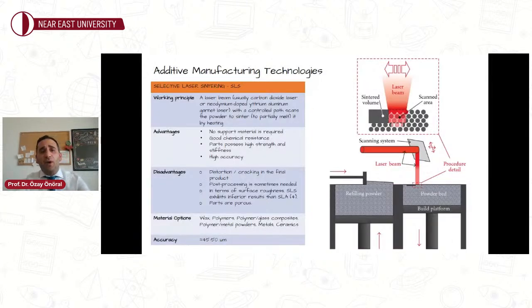SLS technology is another one that is so common in dentistry and allows the creation of 3D models by consolidating consecutive layers of powder, including metallic powders. In this method, a laser beam, commonly a carbon dioxide laser or a neodymium-doped yttrium aluminum garnet laser, can be used with controlled scans to sinter, or to partially melt it by heating. We are not completely melting the metallic powder in this technique, because we have another technique that completely melts these metallic powders, which is called selective laser melting technology. We're going to discuss it later on.